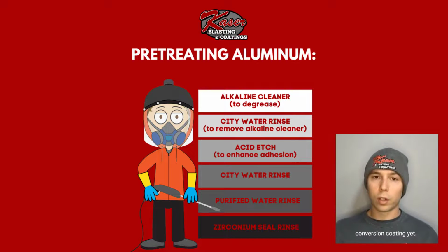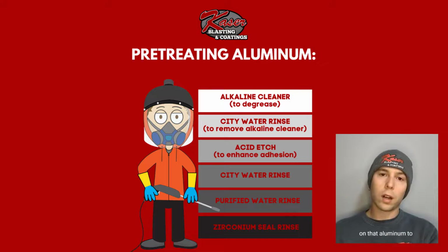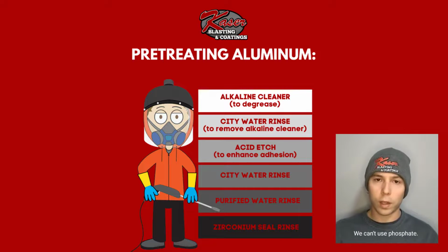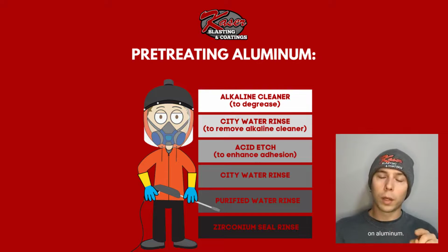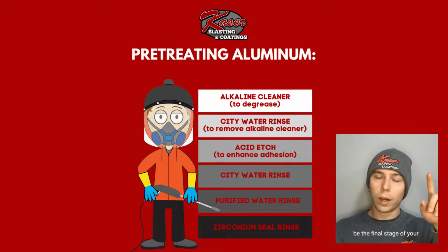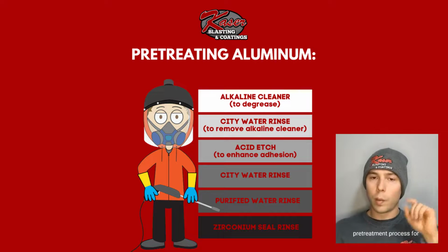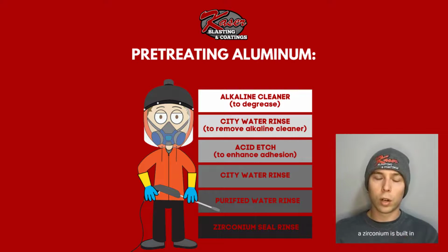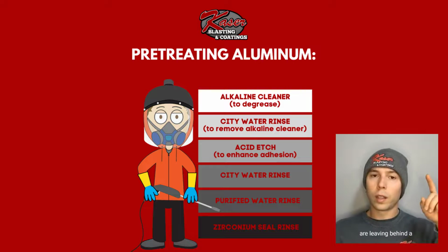We haven't applied any conversion coating yet. We need to put a conversion coating on that aluminum to help promote adhesion and to help with some corrosion protection. We can't use phosphate. We're using zirconium on aluminum. We're building a coating of zirconium on aluminum. That's typically going to be the final stage of your pre-treatment process for aluminum, because usually a zirconium is built in with some sort of sealer, so it's typically a final rinse that your zirconium is in, or if it's not formulated that way, maybe you have another final rinse that is your purified water. So on aluminum, we are leaving behind a conversion coating.